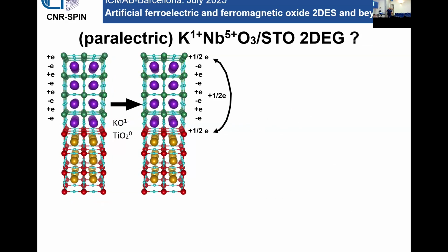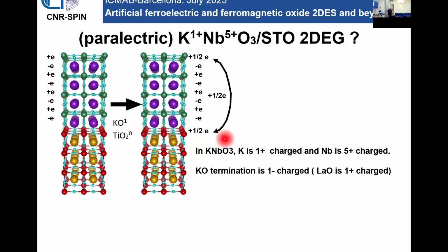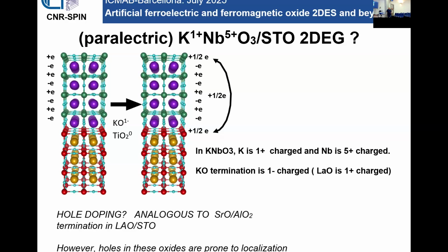In the case of potassium niobate on top of STO, the problem is that the formal charge of potassium niobate is completely different from the charge of lanthanum and aluminum. In particular, potassium is 1+, and you can clearly see that if we grow potassium niobate directly on top of STO, even if it's a paraelectric material, essentially you have exactly the opposite charge compared to the case of lanthanum oxide, titanium oxide interfaces. So this system can be stable only if holes are transferred to the interface, not electrons. On the other hand, it's very well known that in this oxide, in particular strontium titanate, basically a 2DEG is not formed when there is hole doping. A hole two-dimensional system is very difficult to realize with strontium titanate.